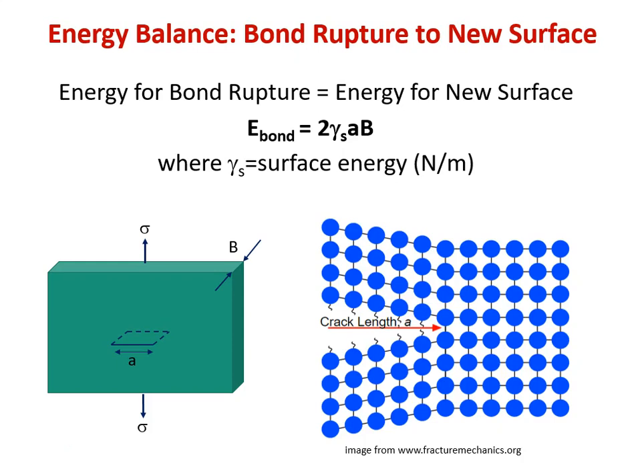So for a given crack, we're looking at, again, a big thick plate of material. It has a thickness of B. It extends out, up and across effectively infinitely. We're going to yank on it with a stress sigma, only in one direction. And it has a crack all the way through of a length of A. So the bond energy that we are overcoming to propagate that crack from a length of A to a longer length, or to initiate it, to create that crack in the first place, more specifically, is going to be equal to the total surface area, which is 2A times B, because you've got a top surface and a bottom in the crack, times the surface energy. And in this case, it's the surface between the material and the air.